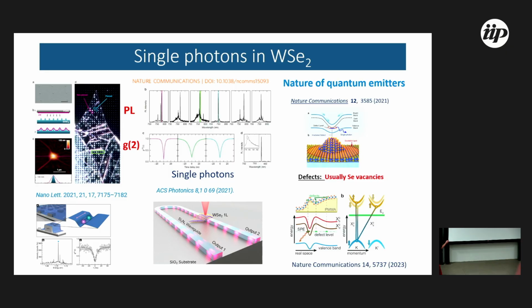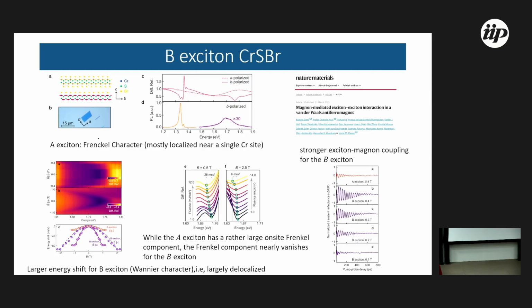This is well known. People use local strain to get these sharp peaks and to integrate with waveguides and photonic systems to investigate single photon emitters for quantum technology. The explanation of these sharp peaks is related to local strain and hybridization of defects. I have investigated this in other works, but it's not the focus. What's interesting is that there is another exciton in CrSBr, studied more last year, which is the B exciton, which involves higher energy bands.